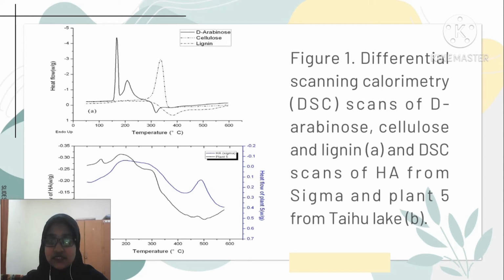Lignin was the only standard material showing corresponding peaks in DSC scans, while monosaccharide and cellulose remain stable in this temperature range. To conclude, F5 peaks in lignin scans behave like transitional peaks between two exothermic processes.